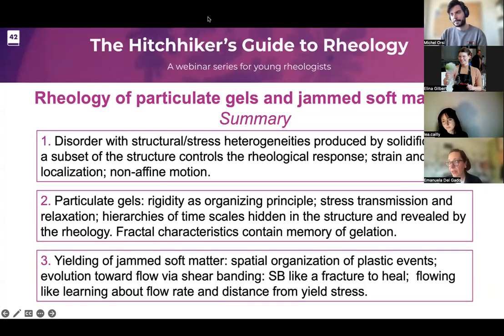So this is a very interesting question. The image of the gel that I was showing before is some version of athermal quasi-static, but it's not quite. So in athermal quasi-static, what you do is that you simulate or represent the behavior of the system under deformation by applying a small step of deformation. Right? And then you let the system find its closest minimum. Usually the conjugate gradient is used to do that in the calculation.